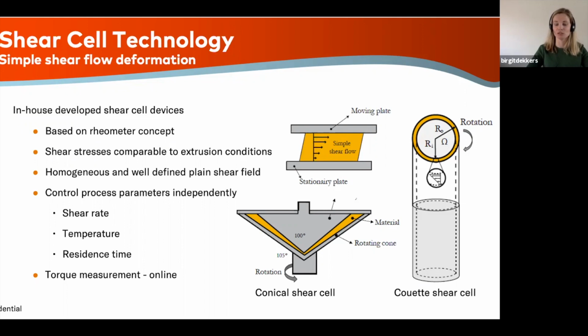Basically, in between these two cylinders, material is loaded. And then the inner cylinder is mostly rotated to deform products. And one of the very nice things of this design, similar to a rheometer, is that you can independently study shear rate, temperature, and residence time. And this is something that you cannot do in a normal extruder, where all these parameters are coupled. And of course, the torque measurement was something very important, and it can be measured over time and online.